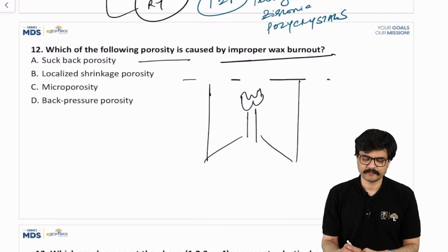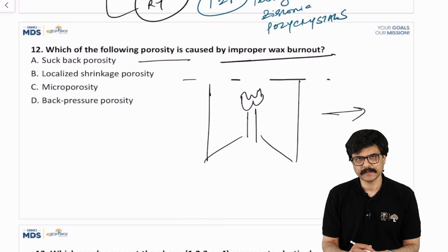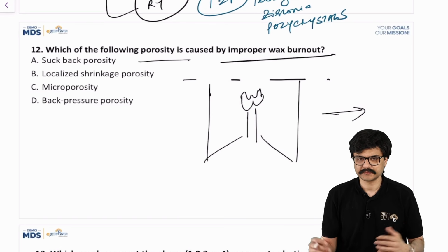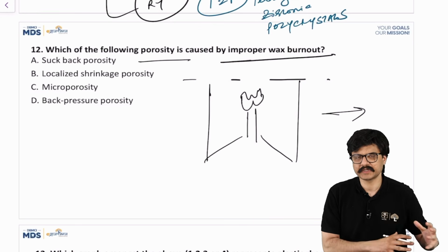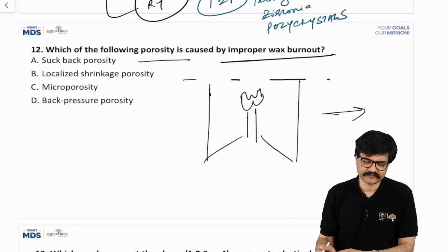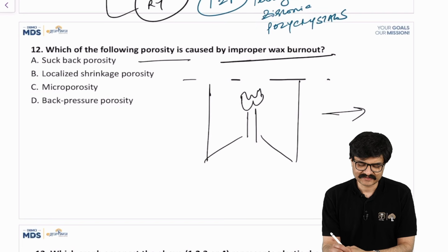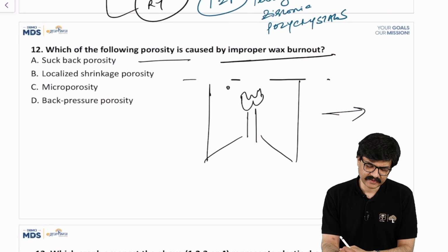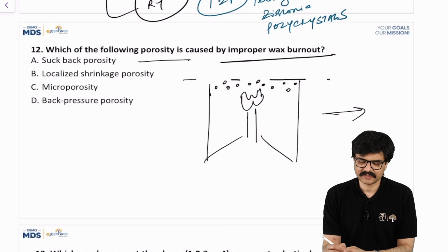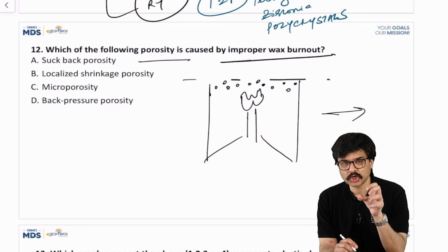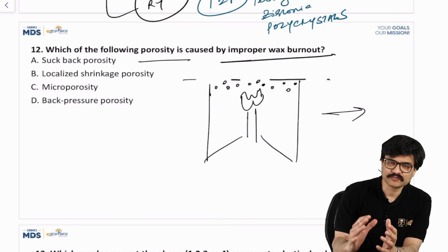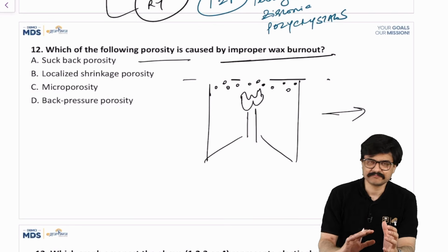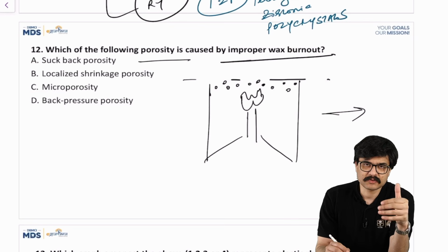All right. Now you place this in the burnout furnace, and you've started your heating cycle. And because of whatever reason, like probably the cycle was of short duration or the adequate temperature was not there, the wax has not completely burnt out. Rather, in the end of the investment ring, whether it's a gypsum bonded, phosphate, or silicate bonded, some of the residue of the wax has clogged the pores. So gases won't be able to completely escape out of the investment mold.